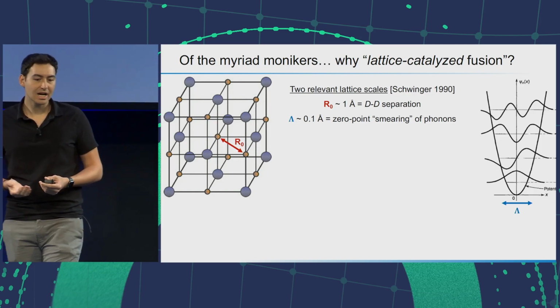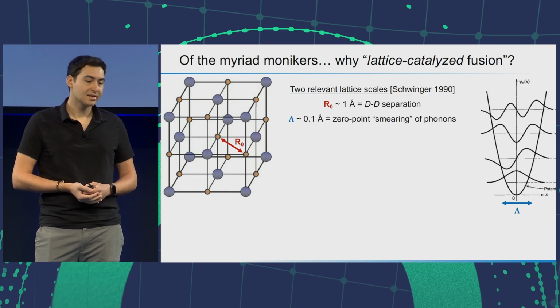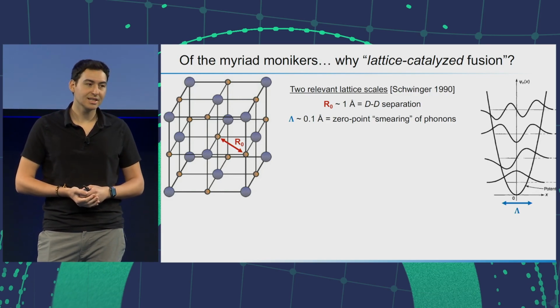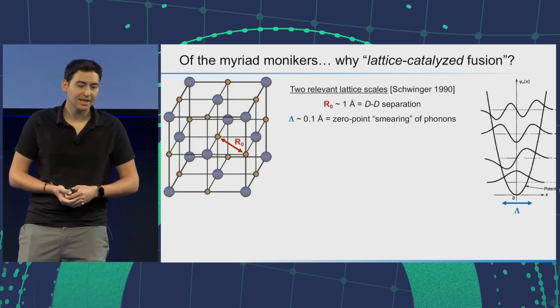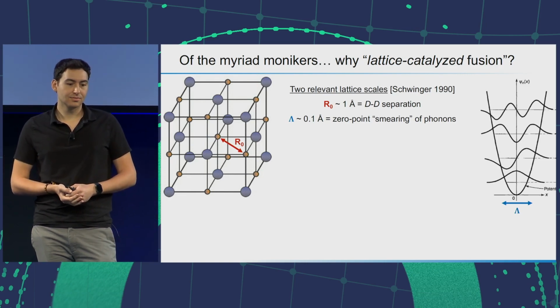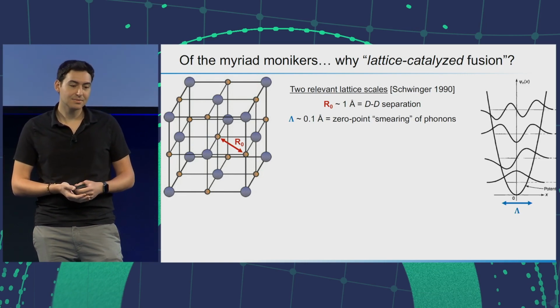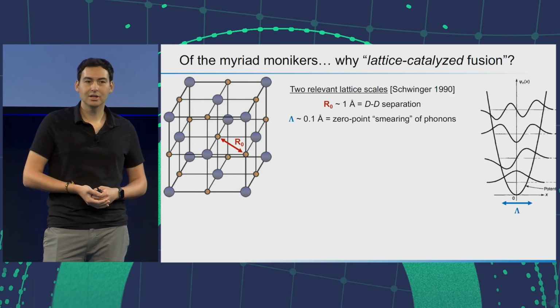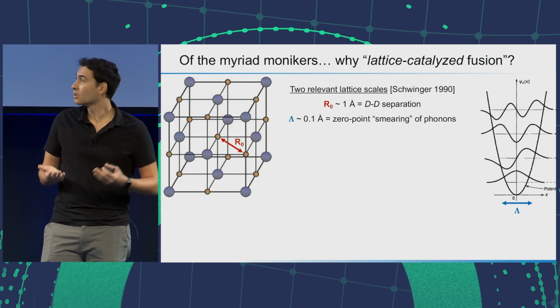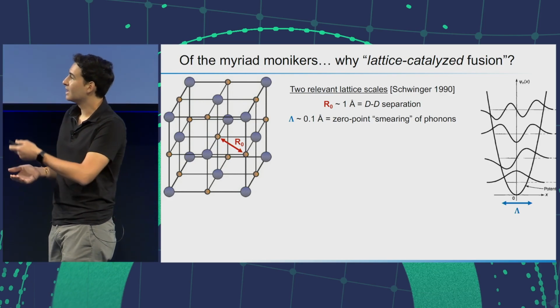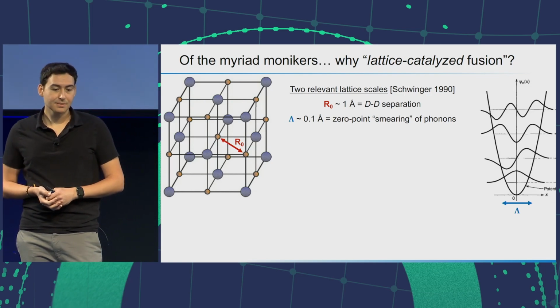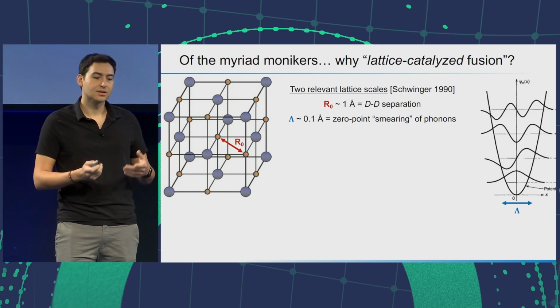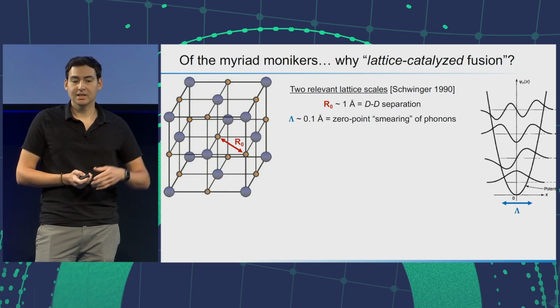The first, let's call it R0. It's the DD separation inside of the lattice, here shown between 2 octahedral sites, a roughly 1 angstrom scale. And then a second lattice scale that comes in, let's call it lambda. I call it for simplicity smearing. You could imagine it like the 0-point motion in a quantum harmonic oscillator well. The bottom there shows the ground state. So these are the 2 scales in the lattice, and their interplay can become important, and it does factor into